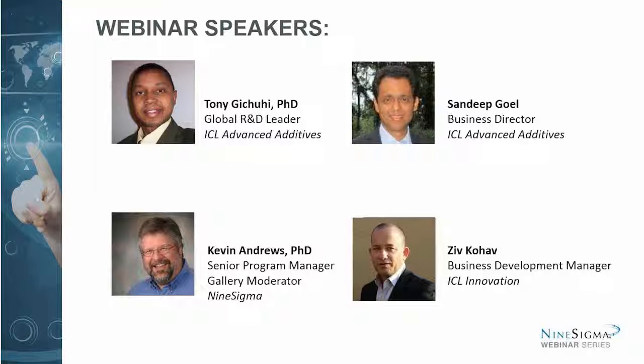Tony, Sandeep? Yeah, so I will tell you today what these coatings are subjected to, and it's not truly representative of what kind of environment they see, but it is what the industry is using as a benchmark. For instance, these coatings will be exposed to salt fog or salt spray environments, and that's really to accelerate the failure mode. Typically, when we expose these test panels in a salt chamber, we will expose them after we've ramped them up to the temperature at which these coatings will see in the field.